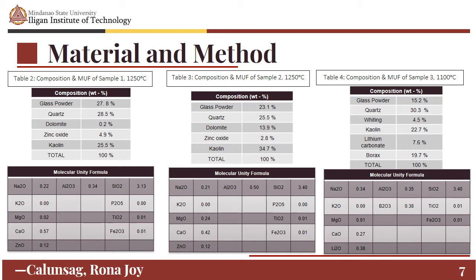And for the molecular unity, here shows that the Na2O has 0.22, the K2O has 0, the MgO has 0.02, the CaO is 0.57, the ZnO is 0.12, and for the alumina we have 0.34, the SiO2 is 3.13, the P2O5 is 0, the TiO2 is 0.01, the Fe2O3 is 0.01.